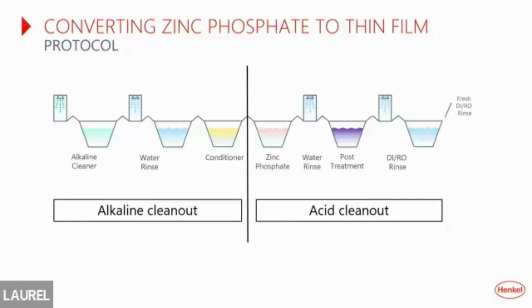And typically, nitric acid is used, although I've seen sometimes sulfuric acid, inhibited hydrochloric acid, and phosphoric acid. But these boil outs, depending on how long or how bad the sludge buildup is in the phosphate bath, can go on 24 hours, sometimes even 36 hours at temperature, 120, 130 degrees.